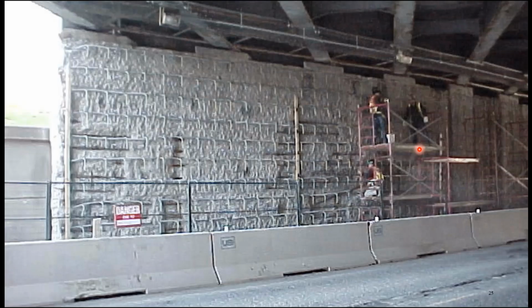The substructures, they used a galvanic encasement. This was the first job of this type that Ontario Ministry of Transportation did. And so they went in, removed any of the delaminated concrete. So you see localized areas here where you can see the reinforcing steel has been exposed. They've roughened the concrete surface. They've put in dowels. They're going to put in rebar, a new cage of rebar. They're going to put in the anode similar to the previous example. And they form and pour the abutments and the wing walls back, but they leave them in service because traffic is on here during this whole process.